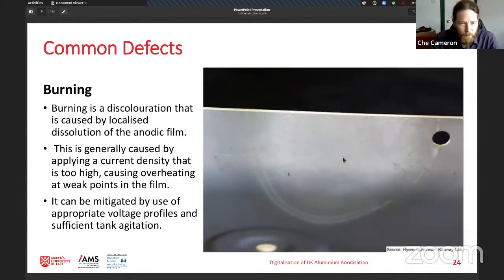Burning is localized discoloration of the film, and this is actually something that would generally be caused by some problems in the anodization process. What usually happens is that there's an overheating at a certain point in the film, and because that anodic oxide is under attack by the electrolyte because it's being dissolved, where that overheating happens, the dissolution happens faster too. So it basically burns its way straight through the oxide and you're left with a rough part. That can be mitigated by using appropriate voltage profiles and making sure that the electrolyte in the tank is being agitated to move around any hotspots and prevent that.